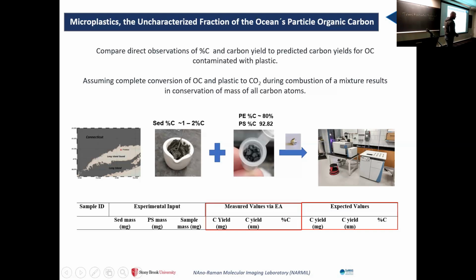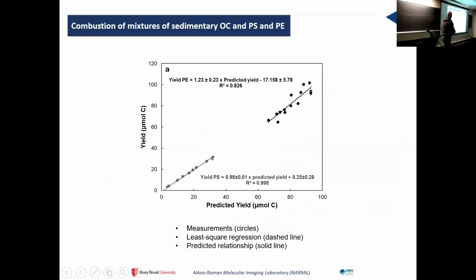And if so, we have a problem, because our equipment is measuring the carbon from plastic and you cannot distinguish that carbon. So you are assuming that all the carbon that came from your sample is biogenic, particulate organic carbon. And that is a problem. So I'm going to give you this result here. This is two different polymers. The gray one is polystyrene, the black one is polyethylene.